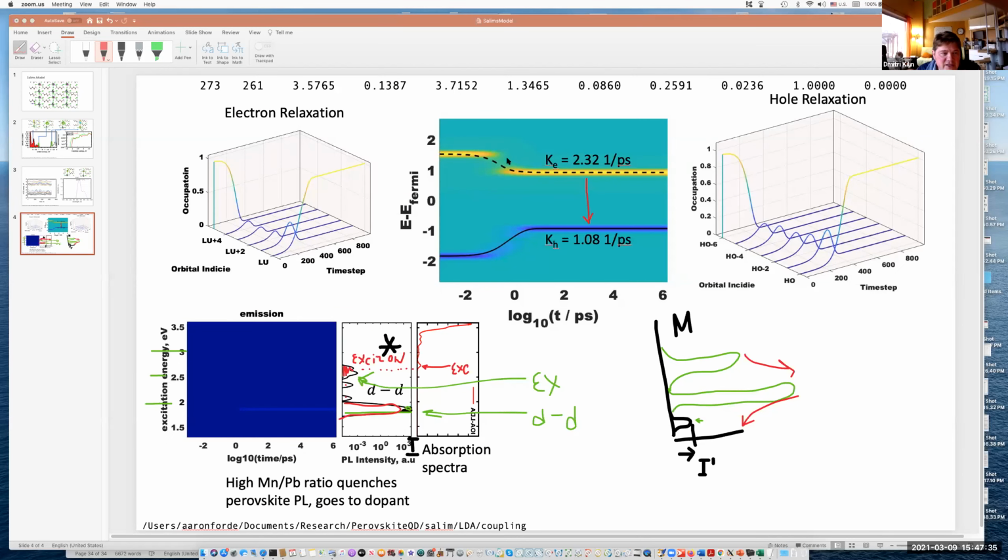So this is the doped model, and this excitation is what we call the exciton. Those regions here are transition states that give these small peaks. Most of the time the system resides on the HOMO-LUMO, which are manganese 2+ localized states, both occupied and unoccupied. There are rates for how quickly it goes from one to another. Aaron gives the numbers here.